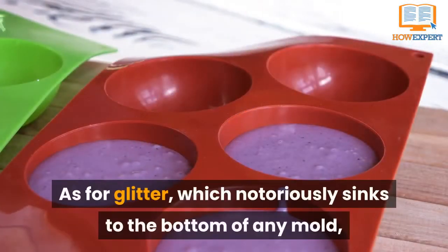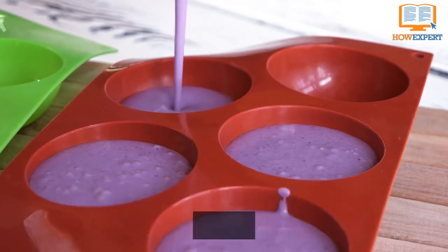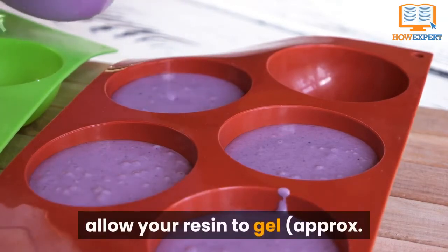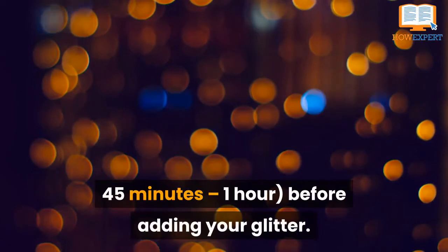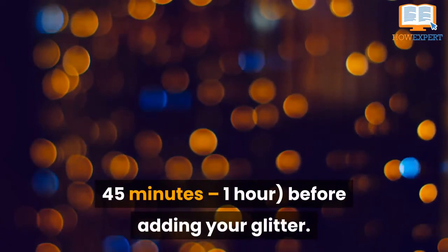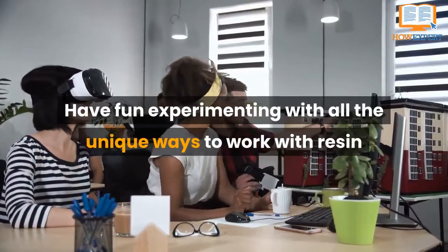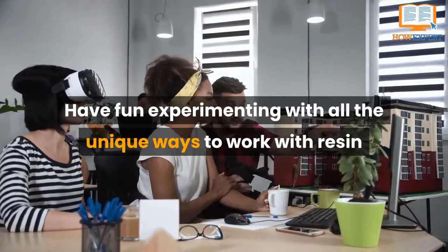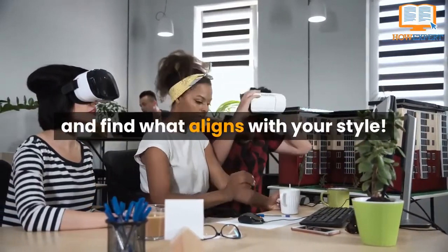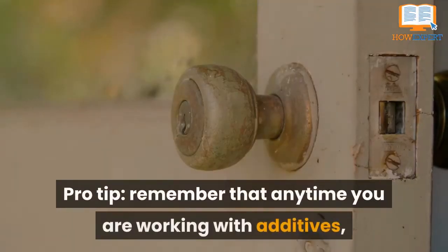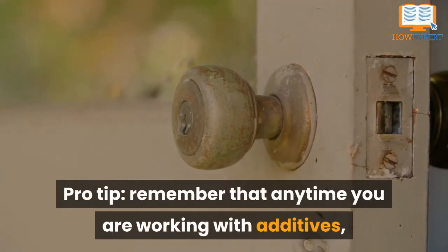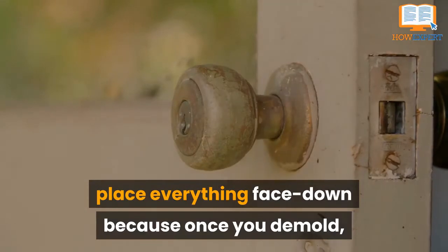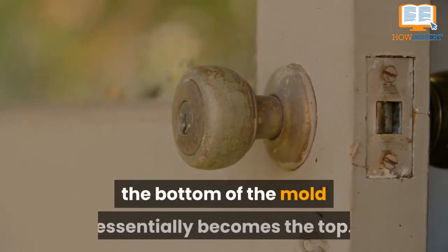As for glitter, which notoriously sinks to the bottom of any mold, allow your resin to gel approximately 45 minutes to an hour before adding your glitter. Have fun experimenting with all the unique ways to work with resin and find what aligns with your style. Pro tip, remember that anytime you're working with additives, place everything face down, because once you demold, the bottom of the mold essentially becomes the top.